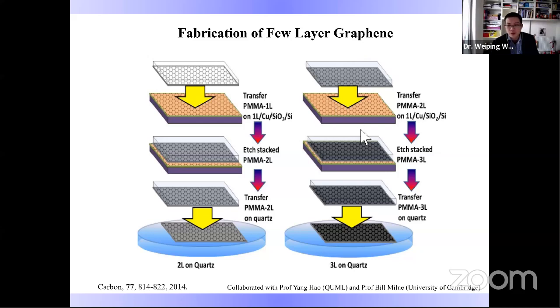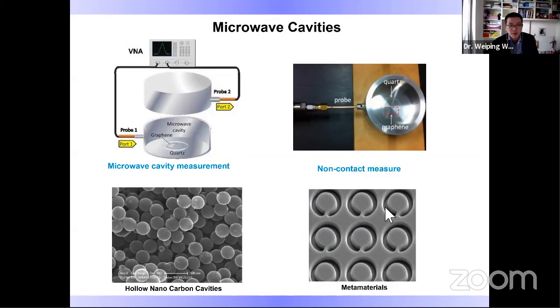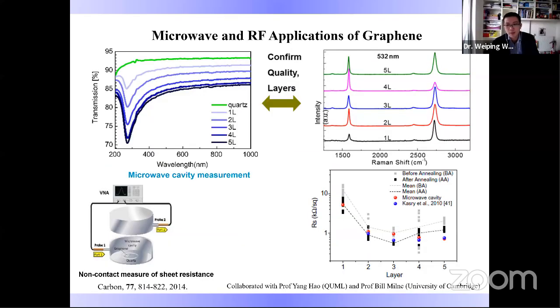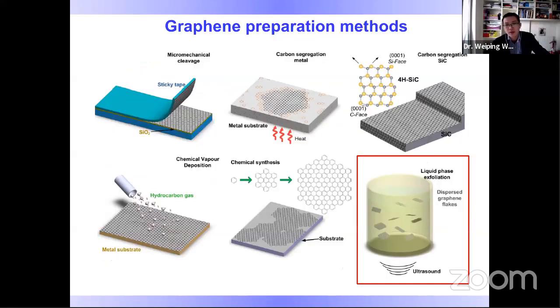onto the quartz substrate to form multi-layer and few-layer graphene on the quartz substrate by repeating. It's a very simple process, just stamping and repeating. We used this graphene or multi-layer graphene as cavity RF devices that lead to some metamaterial research. I'm today going to talk more about the preparation of graphene using solution process.